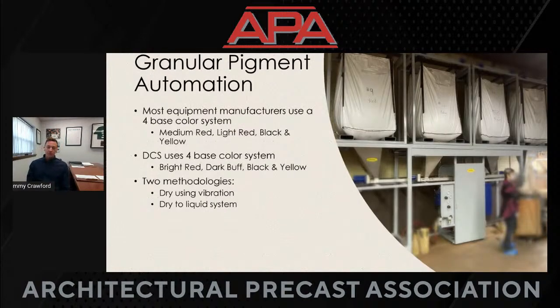Granular, let's talk a little bit about the advantages and disadvantages of granular automation. Most equipment manufacturers use a 4-base color system similar to the liquid side: a medium red, a light red, a black, and a yellow. At DCS, we use 3 synthetics, a bright red, a black, and a yellow, and then a natural dark buff. The idea there is that dark buff produces that limestone color at a low addition rate with white cement.